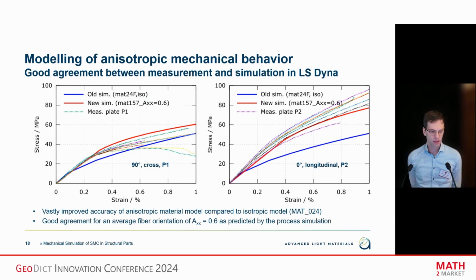And now I come finally to the results, because I see my time is running out. We can actually reproduce the anisotropy seen in the tensile tests. Here in these pictures, the dotted lines are the measurements and the solid lines are two simulations. The blue line is an isotropic model in LS-Dyna, and the red curve is the simulation with the anisotropic material card which we have calibrated.